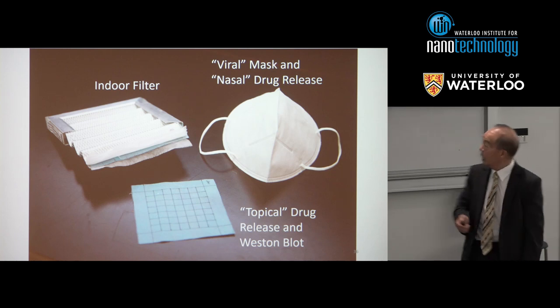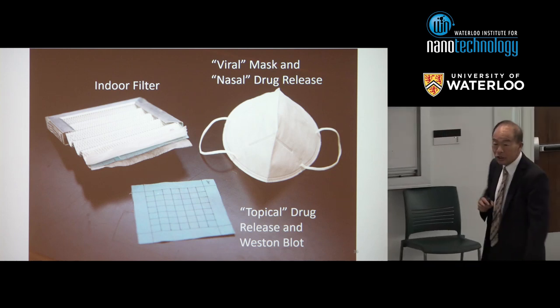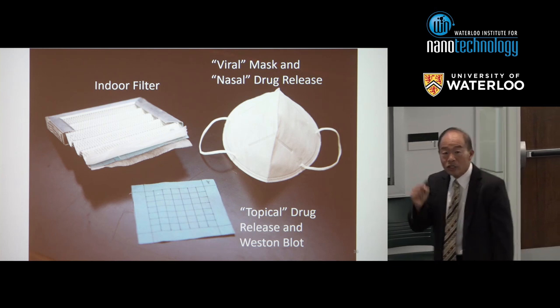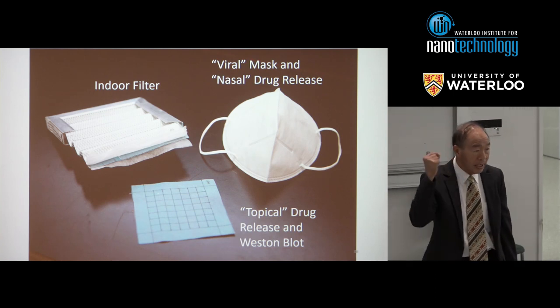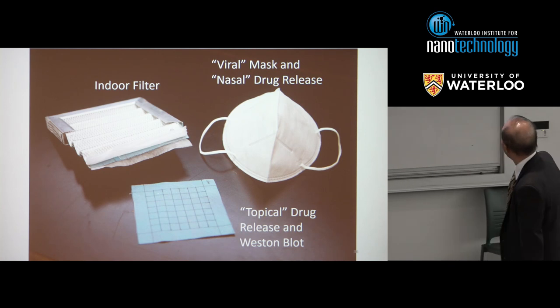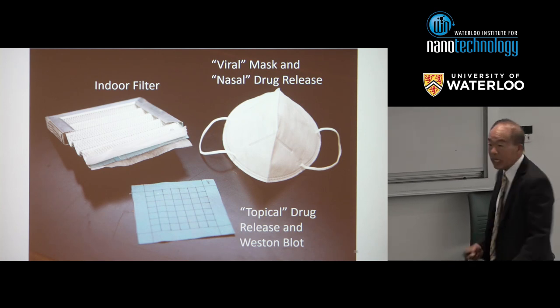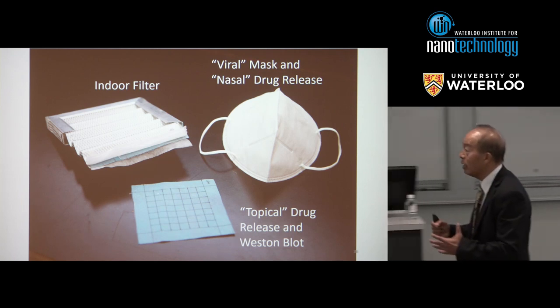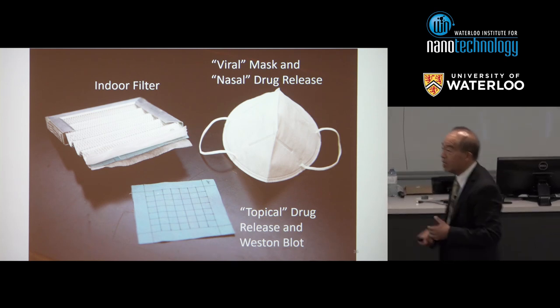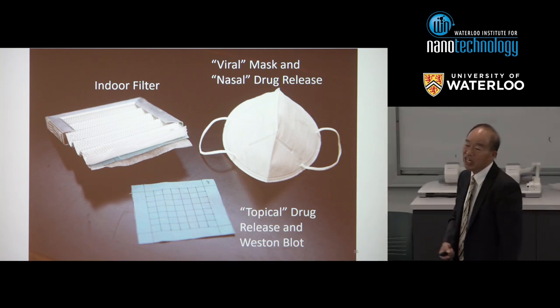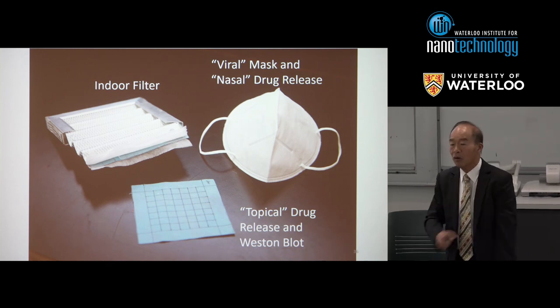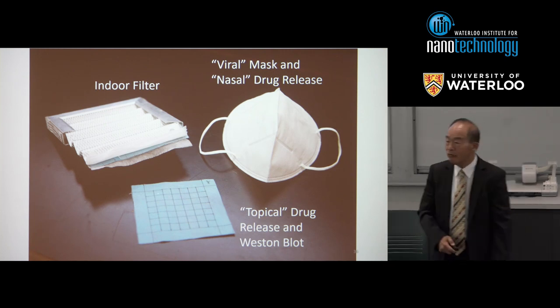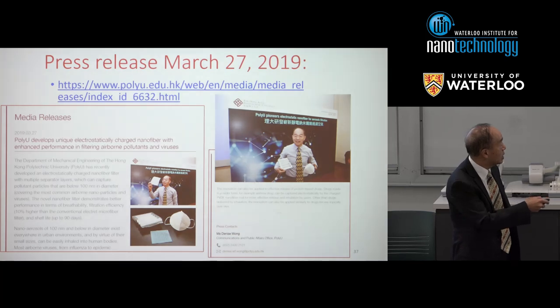Earlier this year we had a news release on this technology. You can put the charged nanofibers into a viral mask — viruses are usually negatively charged, so the positively charged nanofibers are much more favorable for virus capture. You can also use the charged nanofibers for topical drug release — drugs attach via electrostatic charges and release slowly due to humidity — or as a transfer membrane for proteins in western blotting.